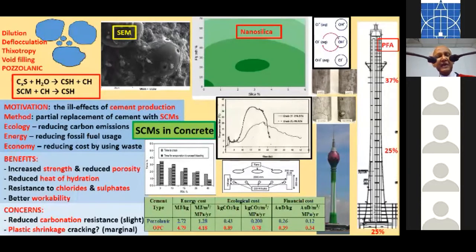So these are some of the benefits. There is increased strength and reduced porosity because of this additional calcium silicate hydrates. Then, like I said, when cement hydrates, there is an increase in the heat of hydration. So there is a lot of heat that is generated. So this is a lab experiment that was done maybe about 20 years ago. This is how, if you have ordinary Portland cement, the temperature will increase. But if you have 25% fly ash, the temperature rise is reduced and also the maximum temperature takes place a bit later. So it is generally better.